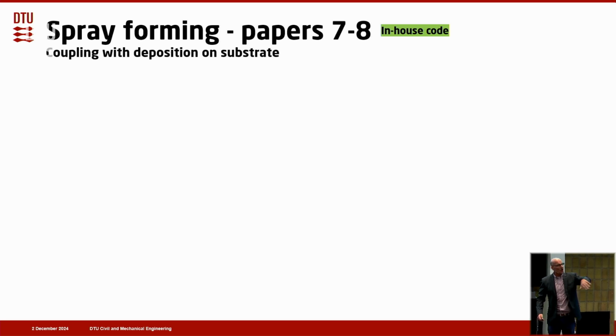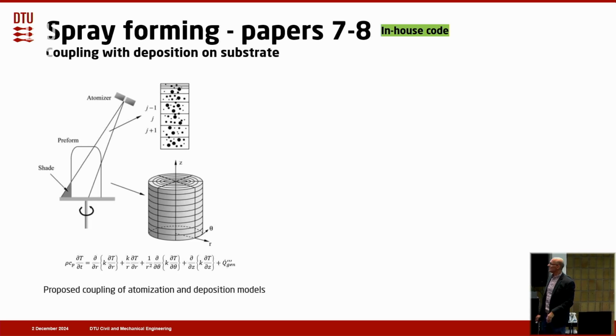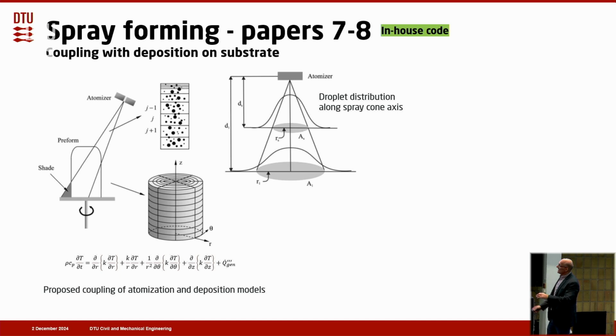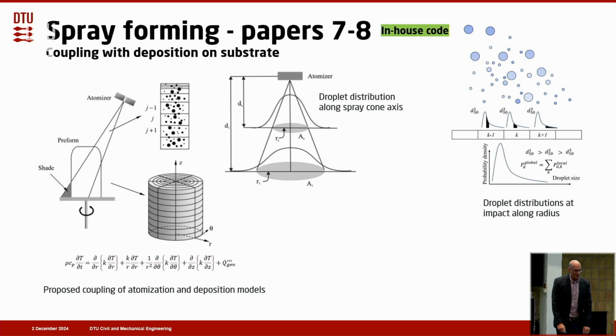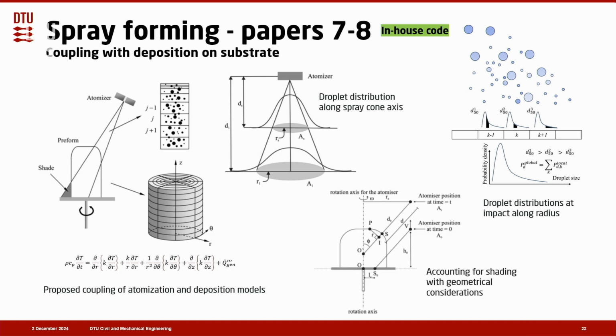This we wanted to couple with the building of the substrate, and this is what you see here, solving the standard heat conduction equation, and then also taking into account the droplet distribution along the axis as well as along the radius. And this is what you see here. And we needed to account for shading with various geometrical considerations as well. That was rather involved at the time. And then we had this coupling between atomization and deposition.